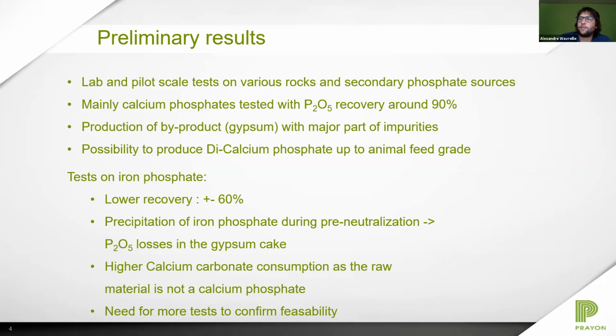Concerning iron phosphate, we tested some materials with high iron content, and we observed lower recovery, with some tests at around 60% yield. We have some problems at this stage. When we do the pre-neutralization, we have precipitation of iron phosphate, so we lose some P2O5, and this also increases the calcium carbonate consumption. At this stage, we need more tests to confirm the feasibility, and we are open to receiving some iron phosphate material and making some lab tests.